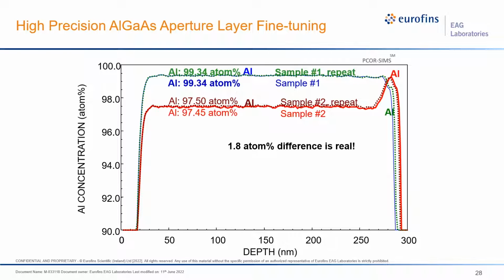And we have used our novel PCOR-SIMS technique to analyze the VCSEL structure with a carbon-doped P-type gallium arsenide DBR, a silicon-doped N-type gallium arsenide DBR, and an undoped low aluminum AlGaAs active layer containing a multi-quantum well. The remainder of this presentation will show how our technique can offer insights into alloy composition profiles, the DBR dopant profiles, and various details of the active region. So let's look at the carbon in a P-type DBR.